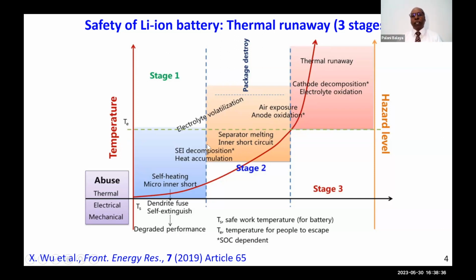If we continue to stay with these abuse conditions, then graphite gets oxidized, the electrolyte gets oxidized and the cathode decomposes, leading to so-called thermal runaway. And there is a limiting temperature. Actually, I have acknowledged this particular reference. I like this particular slide also. There is a limiting temperature beyond which you should not stay. Actually, you should escape from that zone. It's called TE, the temperature of escape, where you have to escape. You shouldn't stay because you can't control the thermal runaway at all.